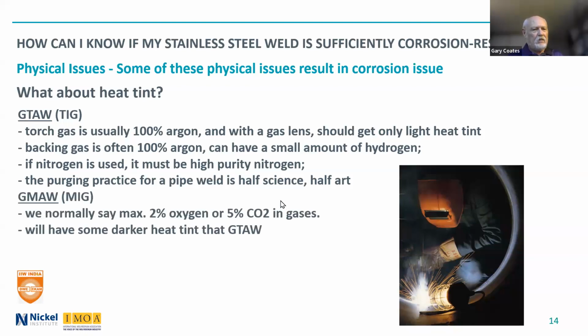With MIG welding, we normally say maximum 2% oxygen or sometimes 5% CO2 in the gases. That's okay for 304L, 316L. I wouldn't do that on the higher alloyed stainless steels, but they do give a darker heat tint than you get with gas tungsten arc welding. And many of the other processes don't protect the heat affected zone. And that is in some ways the most important area we're concerned about from a corrosion point of view, the heat affected zone, the reduction there caused by heat tint.